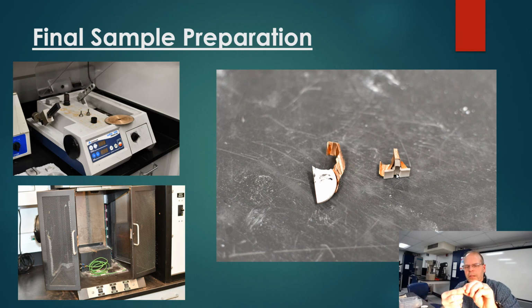We have these little tiny plastic clips that are going to hold the sample in place. So what we end up with is a little ceramic piece being held by the plastic clip. Now, one thing I want to point out to you, these are going to be viewed in the scanning electron microscope, and the scanning electron microscope depends on conductivity. You have a sample that's not conductive, right? So again, what we have to do is two things. We carbon coat, we spray a little bit of carbon on these samples, or sometimes we just use a little sticky tab at the bottom, just to give some conductivity for our scanning electron microscope. But we also use this copper foil, which we are going to ground so our signal has something to go through. So that's kind of what you're looking through.